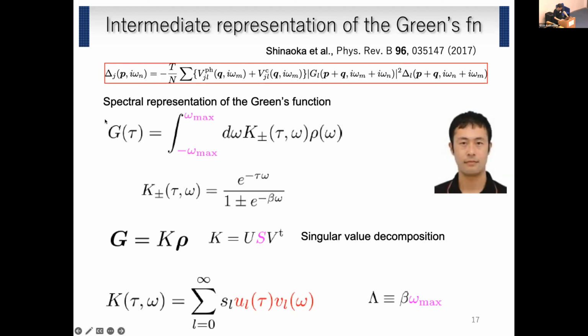We start with the spectral representation of the Green's function here. And this is the kernel, and we do a singular value decomposition for this K. And we introduce these bases. Shinaoka and others found that if we expand the Green's function in terms of U or V, then the number of bases can be as small as 30 or 40. And if we introduce 30 or 40 bases, then the Green's function, tau dependence or omega dependence, can be reproduced very accurately.